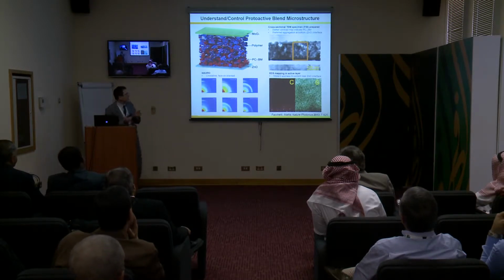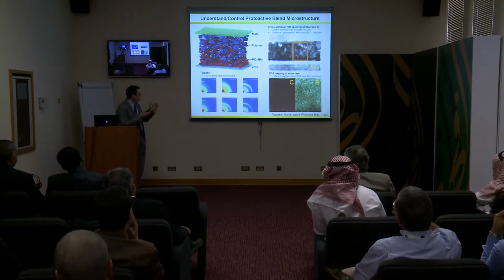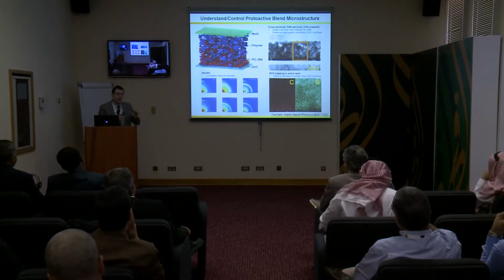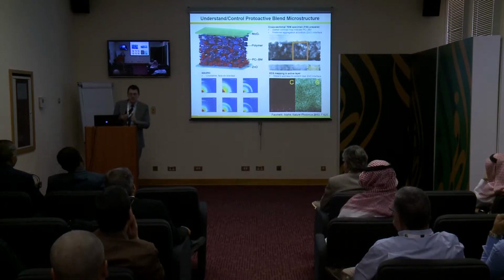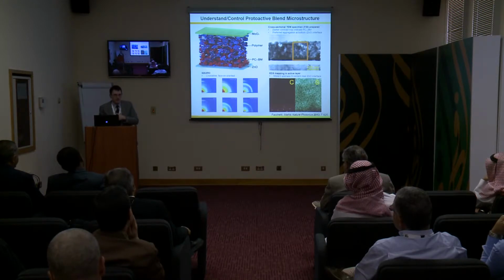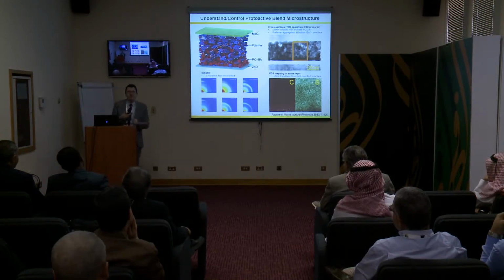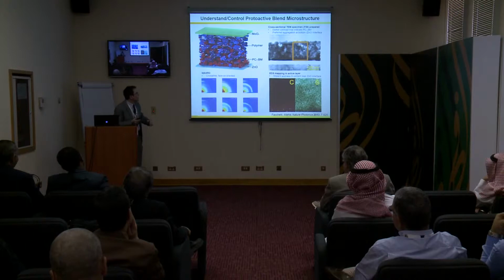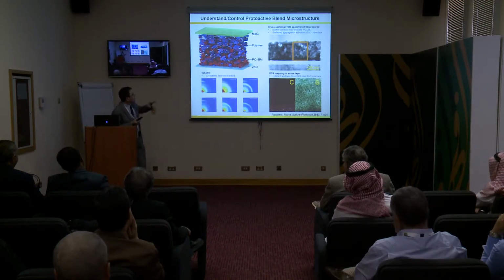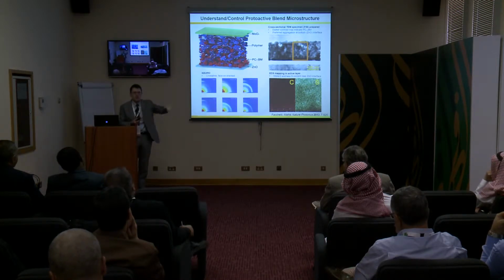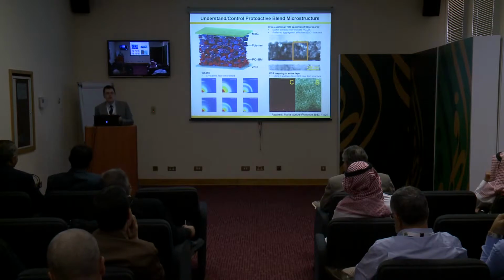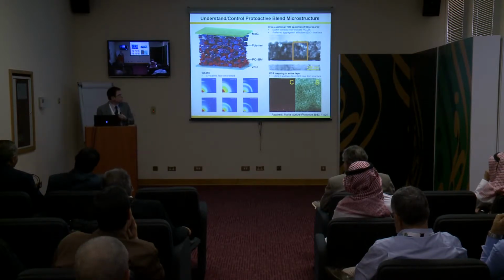So having a combination of phase gradation, phase separation, and the right morphology of the polymer was a sort of the right recipe, which we did not invent. It was discovered. It just happened. There was nothing to invent. So it was a good morphology. It has a huge drawback. If you take this blend and you heat it up at 120 degrees for 5 minutes, the efficiency and the fill factor drop about 50–60%. So it's not a very stable morphology.